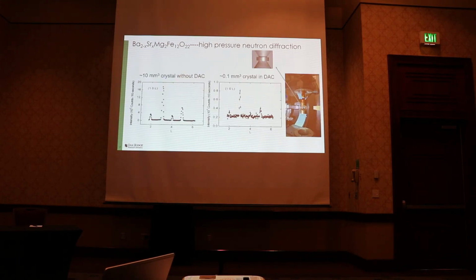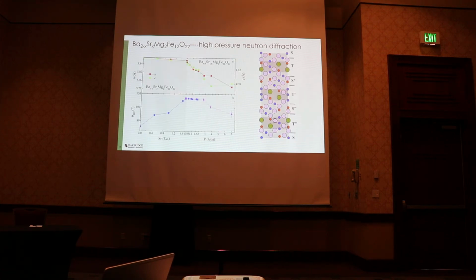This is three minutes. Okay, maybe quick. With the diamond cell, we cannot measure quite big crystals, but it's still doable. What happened is here: with the pressure and doping, we keep the lattice parameter going down, and what happened? The turn angles didn't go up, actually going back.